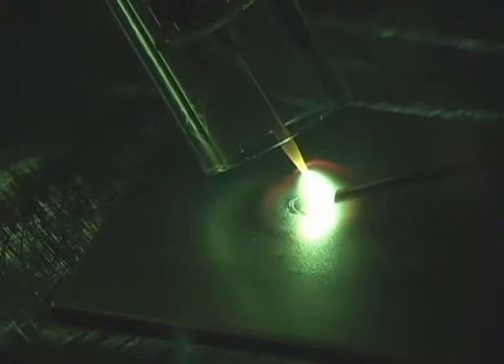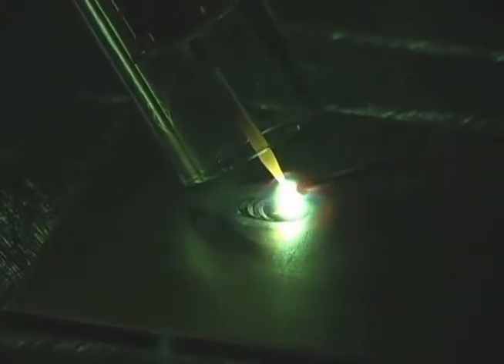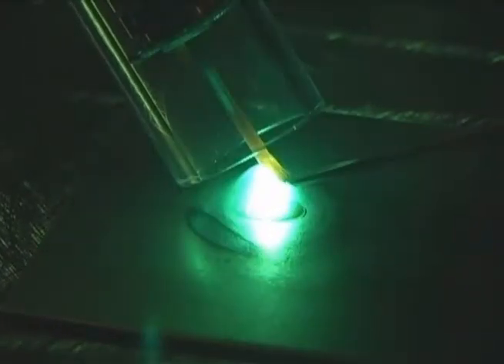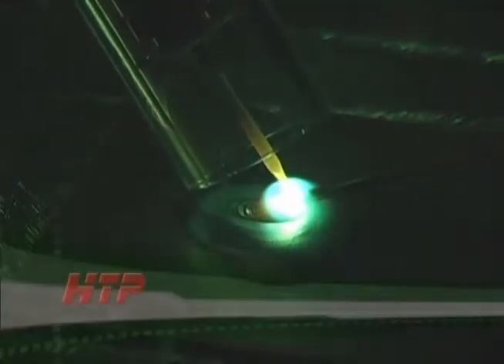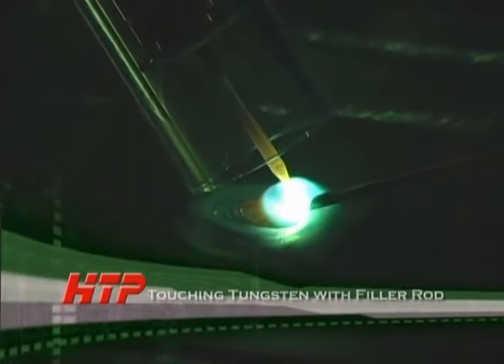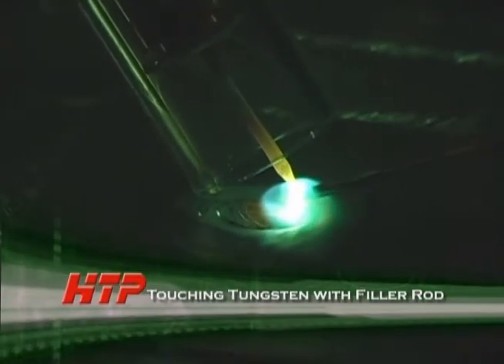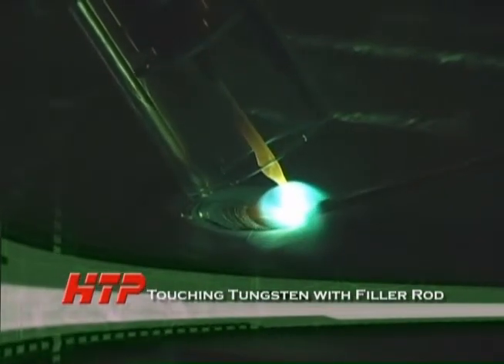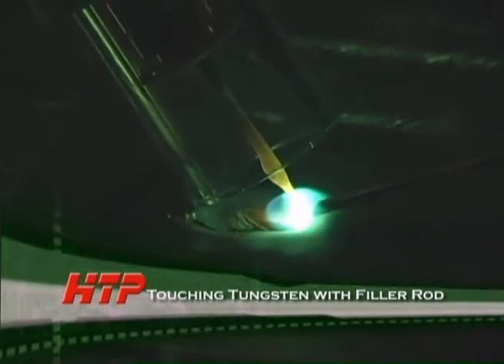We start welding, going along fine, and then it happens. You wobble a little and hit the tungsten with the filler metal. The tungsten is so hot it immediately melts the filler metal. The color of the arc changes to kind of a bluish halo, and the shape of the arc changes from a cone to a sphere.